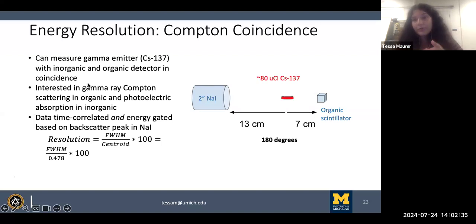But if you're trying to go more so for energy resolution, you might want to look at a different detector, right? Organic scintillators can also be PSD capable, so they could detect neutrons and gamma rays at the same time, or even other particles too. And so if you want that all in the same platform as well, organics are good. Now, organic glass scintillators themselves stand apart among their own group because they're an amorphous solid, so you don't have to physically grow them like a single crystal. Their ability to remelt and reconstitute, and their high performance. Their performance is very high, so that's been a very encouraging thing as well.